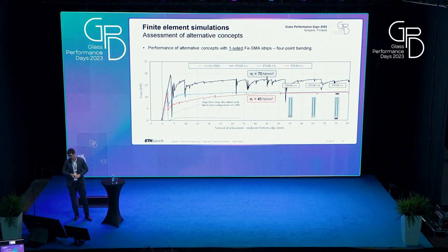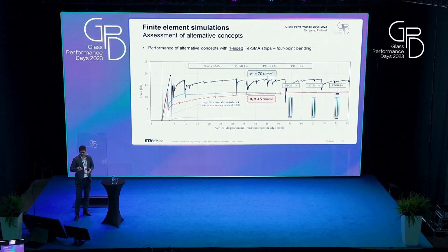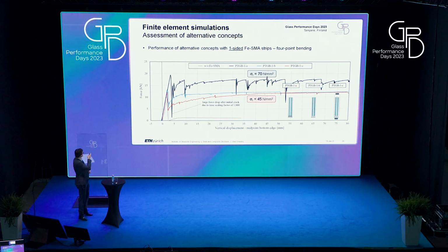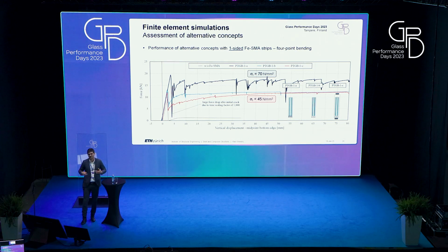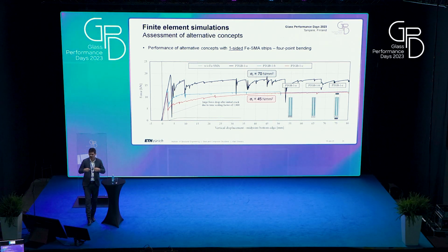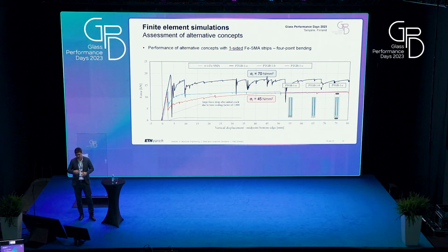And for the ones with one-sided strips, the results look pretty similar. These larger drops in the case of the first crack are due to the time scaling factor that we used in the simulation. If we would reduce the loading speed in the simulation in that range, this drop would disappear at some point. So this is like a dynamic effect that we have there.